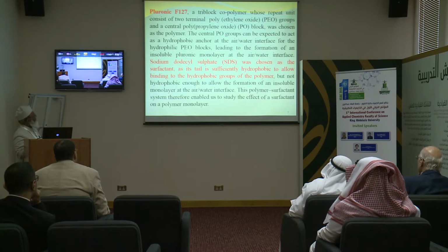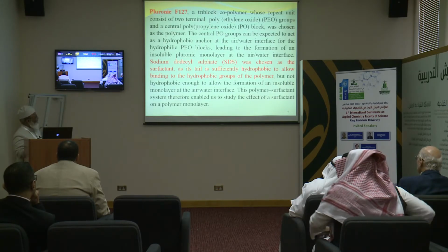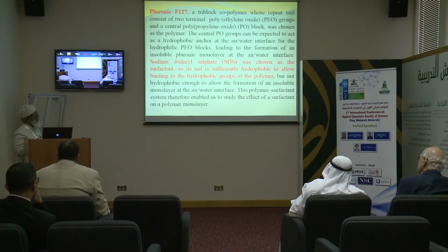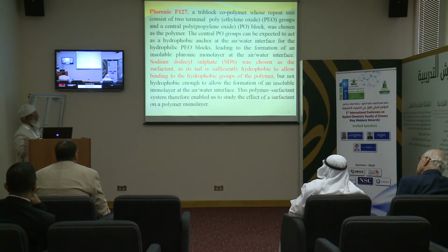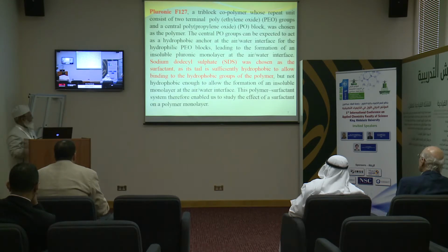The central polypropylene oxide groups can be expected to act as a hydrophobic anchor at the air-water interface for the hydrophilic PEO blocks, which lead to the formation of an insoluble Pluronic monolayer at the air-water interface. The sodium dodecyl sulfate (SDS) was chosen as the surfactant, and its tail is sufficiently hydrophobic to allow binding to the hydrophobic groups of the polymer, but not hydrophobic enough to allow the formation of an insoluble monolayer at the air-water interface. This polymer surfactant system therefore enabled us to study the effect of the surfactant on the polymer monolayer.